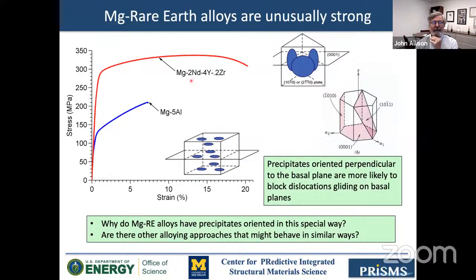Compared with these magnesium aluminum alloys, when you age those, the precipitates lie in the basal plane. And so then they are less effective at blocking slip. So we know that, and that's why they're strong. But why are these precipitates oriented orthogonal to the basal plane, or actually parallel to the prism plane? And are there other alloying approaches that might behave in similar ways? Because rare earths are expensive, and so we'd like to minimize their use for things like automotive applications.